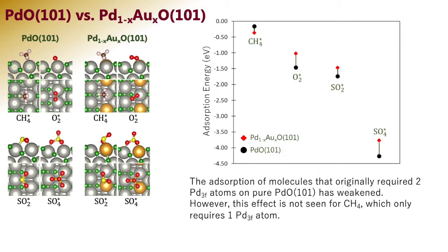Similarly, it was shown that the formation of dissociated O plus O adatoms on palladium oxide is thermodynamically less stable than for the molecularly adsorbed O2 and is kinetically limited by the high activation barrier for O2 dissociation. So I do not show the adsorption of atomic oxygen here.